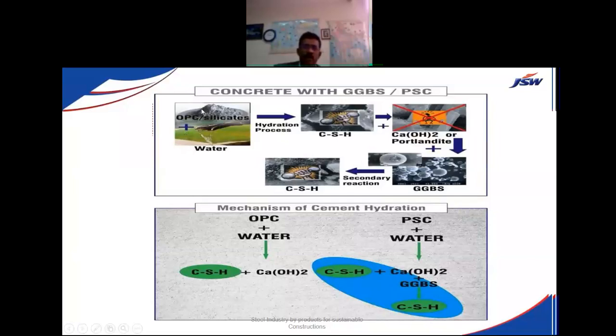When we have OPC cement with water, we have a reaction called an exothermic reaction, where we get calcium silicate hydrate gel. It's the DNA of the concrete. Then we get calcium hydroxide. This is about 25% calcium hydroxide, which is the weak component. I can say it's a cancer cell in the body. If it is there, it starts leaching out. You can see white patches coming out after 3 to 4 days of concrete making. This is called calcium hydroxide. So this is detrimental. Generally, sulfates, chlorides and carbonation happen because of this product.